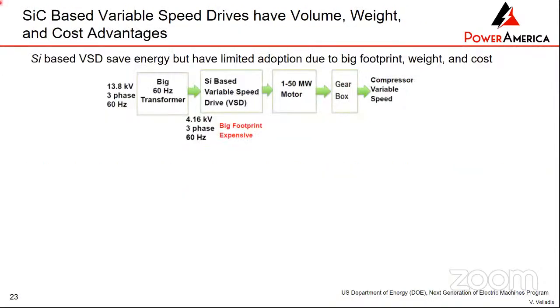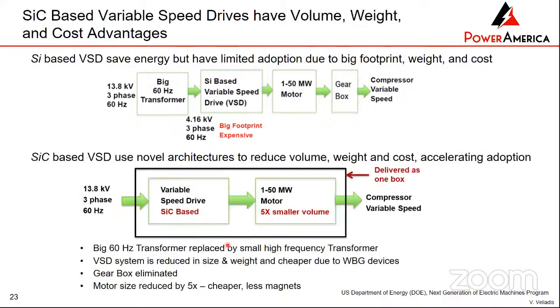So what you want to do is go from the fixed frequency motor to the variable speed motor, and that will make it more efficient. If you make it out of silicon, the traditional power material, it's very, very lossy. If you follow the silicon carbide solution, you can go directly from the high voltage grid at 14,000 volts into a variable speed drive that's being enabled by silicon carbide, and then you have a variable speed compressor for the motor, which will save you a lot of energy. So that's another big application for silicon carbide.